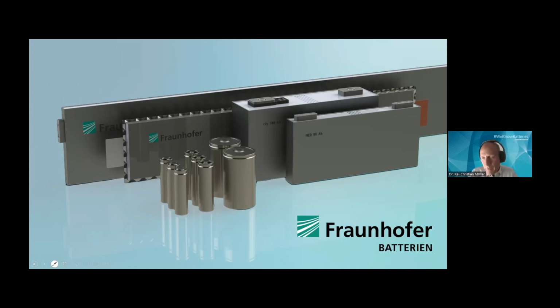Yes, exactly. The graphite has to take up the lithium ions, and these diffusion processes have limits. If the currents are too high and the temperature too low, the lithium ions cannot go so fast into the graphite structure because they have to fill up these graphene layers. So you have something like a traffic jam in front of the graphite particles and a lithium metal deposition, which can form dendrites and give short circuits.